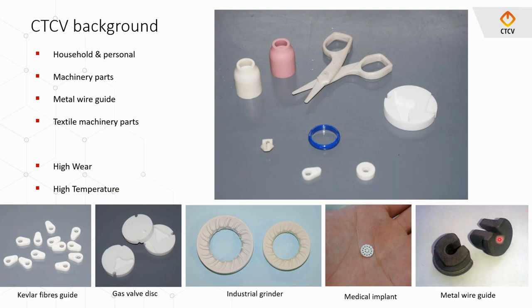And also we have here a tungsten carbide that we can consider like a ceramic one because of the hardness. We have some experience as well in cemented carbides with cobalt as the binder. Okay, and you can see how tiny we can mold the part and go to the maximum of the size allowed in ceramic injection molding.